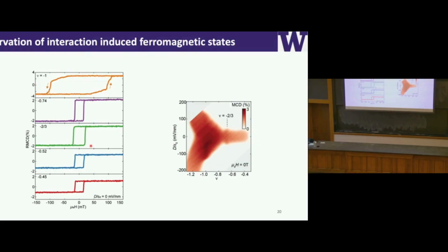That's exactly what we did. Here I show you a few different curves. We measure the circular dichroism as a function of magnetic field, swept forward and backward, on the horizontal axis. Each panel here is taken at a different filling factor. The top is filling factor -1, for example, and the green is -2/3. You can see there's a pronounced hysteresis for each filling factor. That really demonstrates we do have a spontaneous ferromagnetism that breaks the time-reversal symmetry.